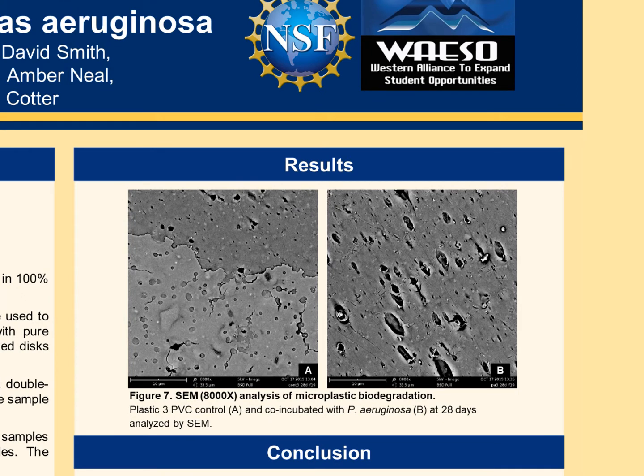Figure 7 is an SEM analysis of microplastic biodegradation of plastic 3, PVC, co-incubated with Pseudomonas aeruginosa at 28 days. We can see a significant difference in pore size. Due to the porosity of PVC, Pseudomonas aeruginosa can anchor itself into these holes and better colonize the PVC surface. We believe this is the reason for our increase in porosity shown on the right side.